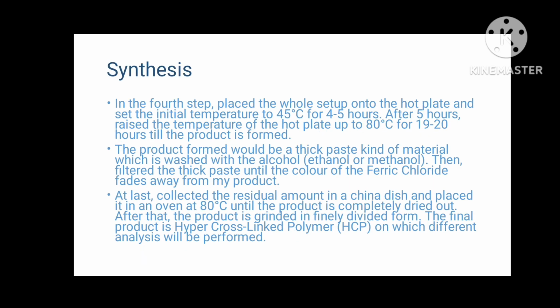Next, we have to put the oil bath on the hot plate and set the temperature at 45 degrees centigrade for 4 to 5 hours. After 5 hours, increase the temperature of the hot plate up to 80 degrees centigrade for 19 to 20 hours till the product is formed. How will we know that our product is formed? The liquid texture of all the chemicals shifts towards a paste-like material. When we get thick paste-like material in our round bottom flask after about 19 to 20 hours of heating at 80 degrees centigrade, then we are getting our product.